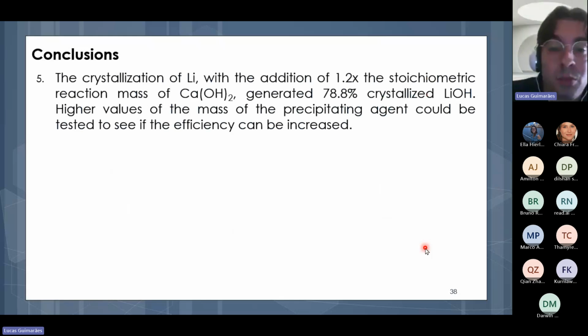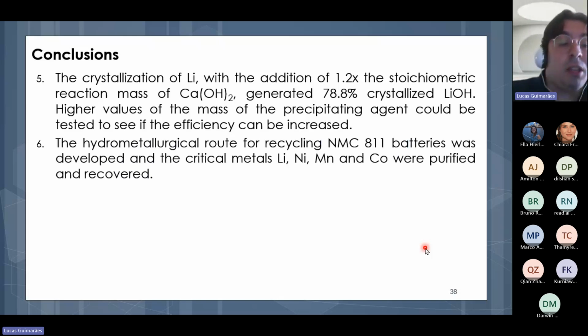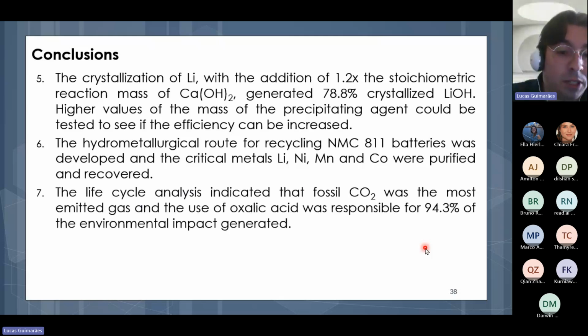The crystallization of lithium, with the addition of 1.2 times the stoichiometric reaction mass of calcium hydroxide, generated around 79% crystallized lithium hydroxide. Higher values of the mass of the precipitating agent could be tested to see if the efficiency can be increased. The hydrometallurgical route for recycling NMC 811 batteries was developed, and the critical metals lithium, nickel, manganese, and cobalt were purified and recovered.